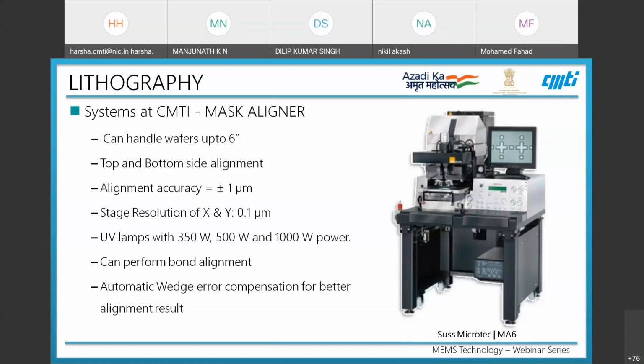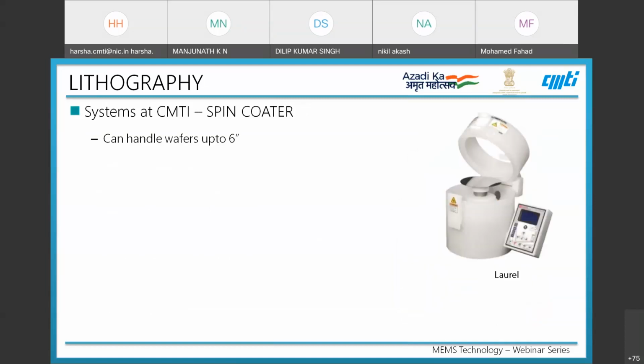We have a mask aligner which can handle up to 6-inch wafers, from Suss Microtec MA6. It has both top and bottom side alignment with an alignment accuracy of 1 micrometer, and different UV lamps with 350 watts, 500 watts, and 1000 watts power. It can also perform bond alignment and automatic wedge error compensation for better alignment results.